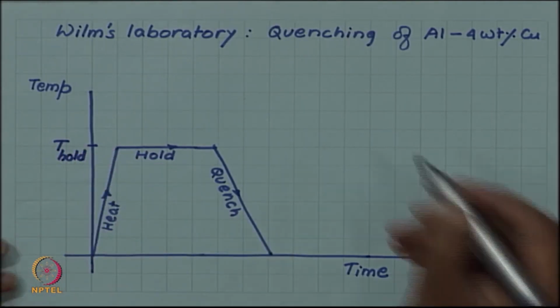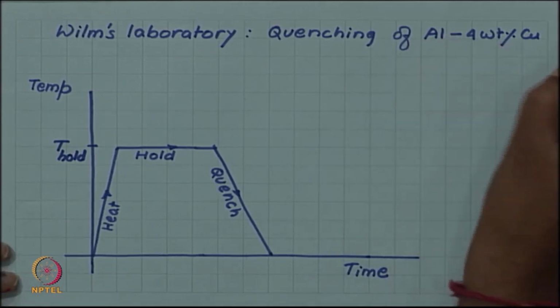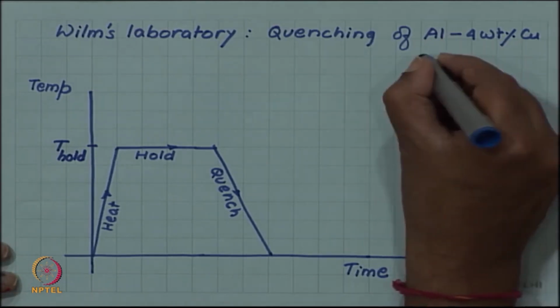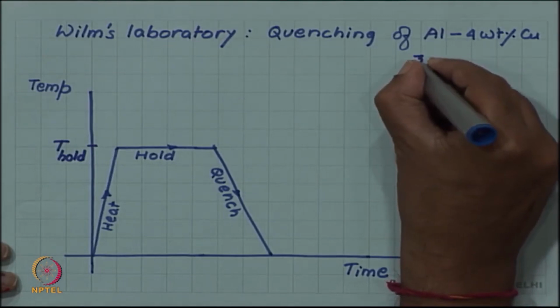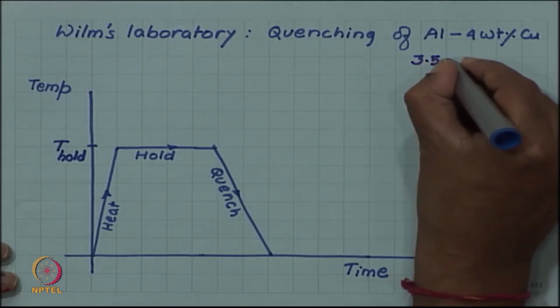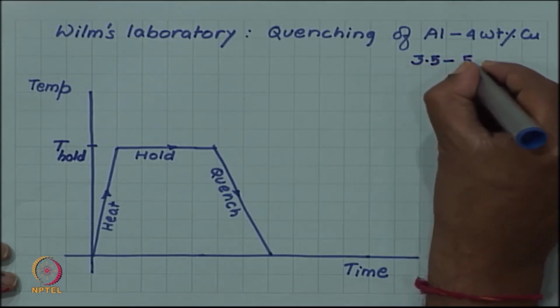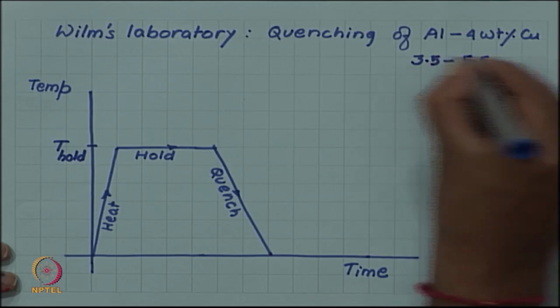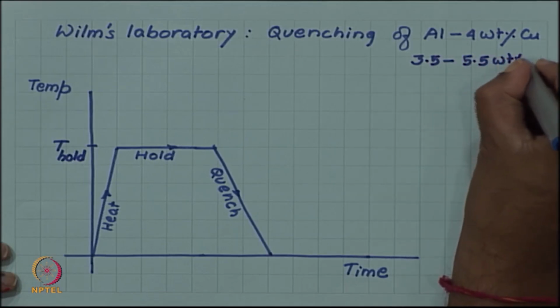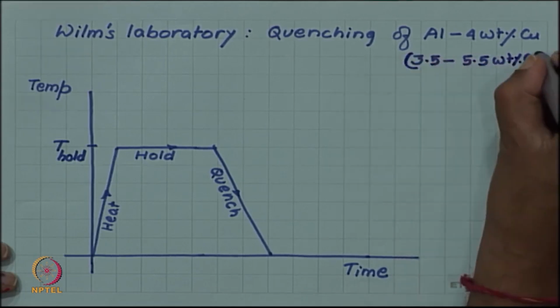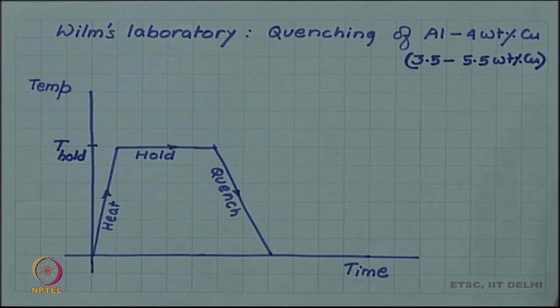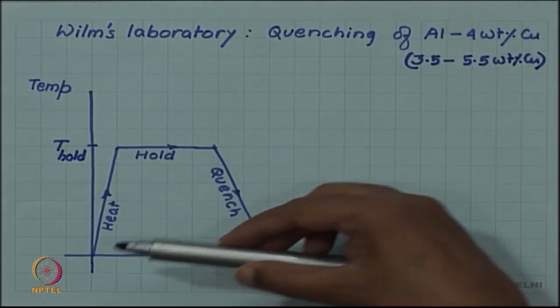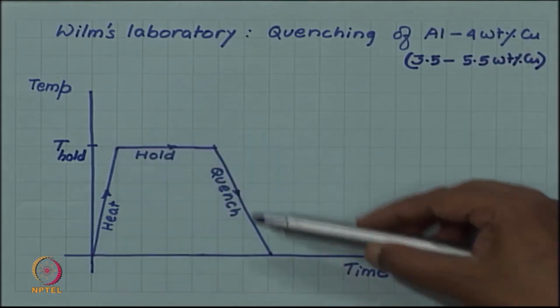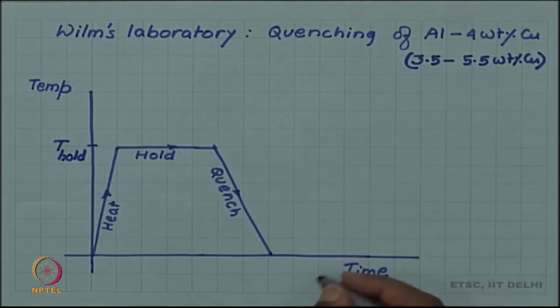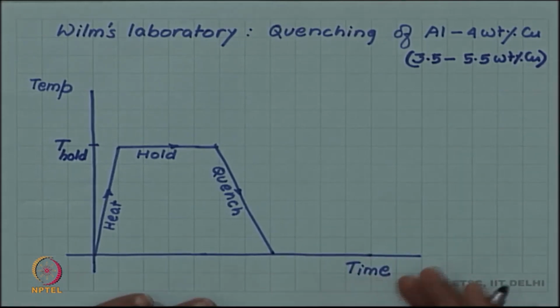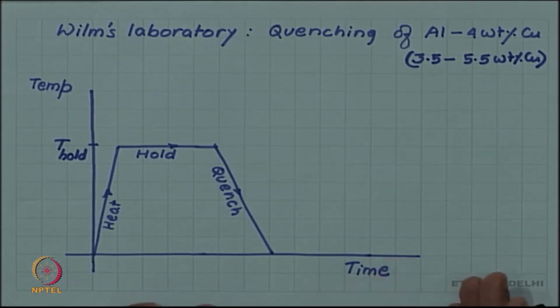So, he made a range of aluminum alloys, in particular aluminum 4 weight percent copper alloy. The copper percentage he actually tried from anywhere from 3.5 to 5.5 weight percent copper. So, he made several alloys and then he attempted this heat treatment, heat, hold and quench, and then measure the hardness. However, initially he had no success.